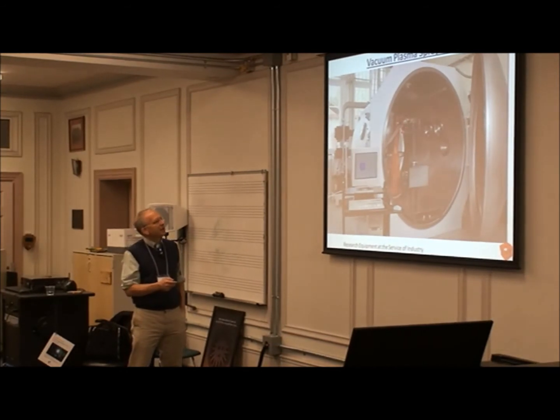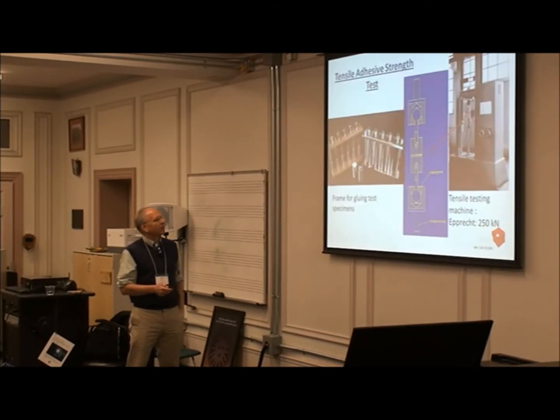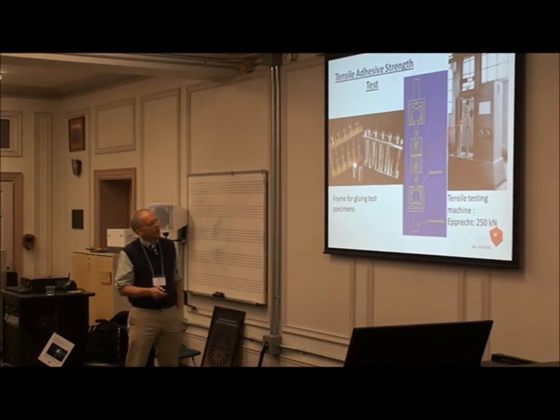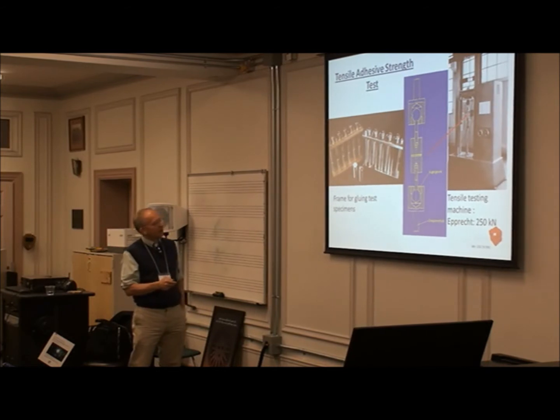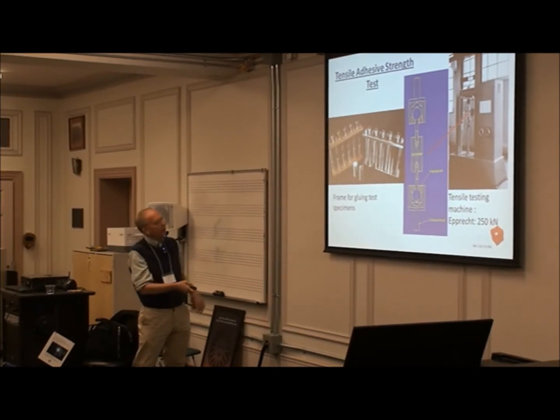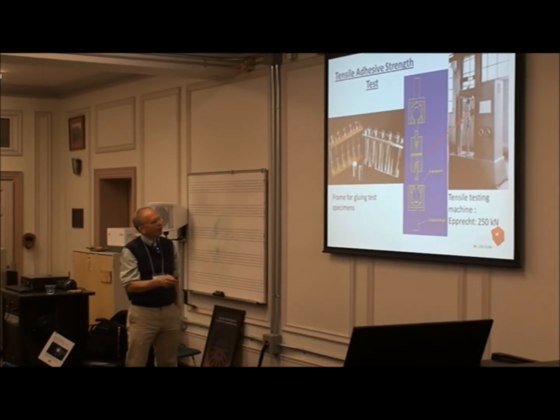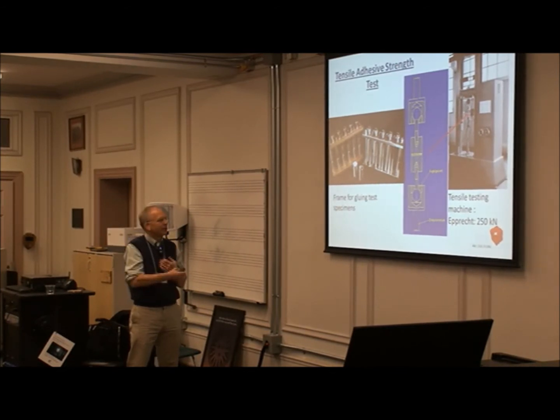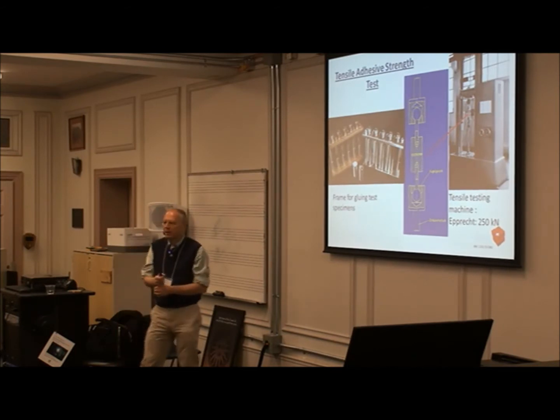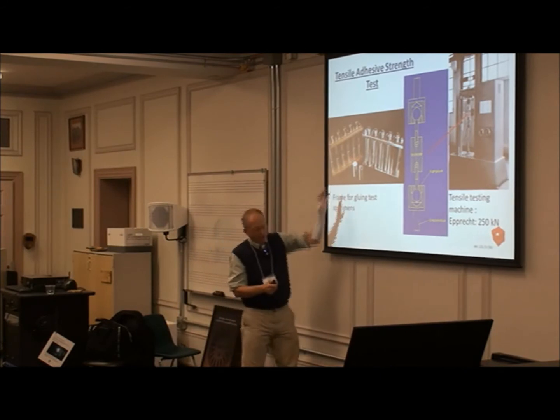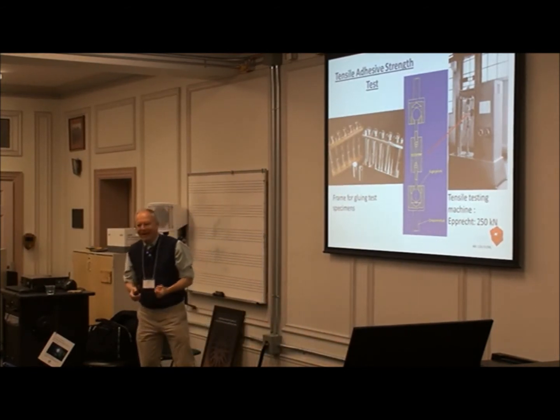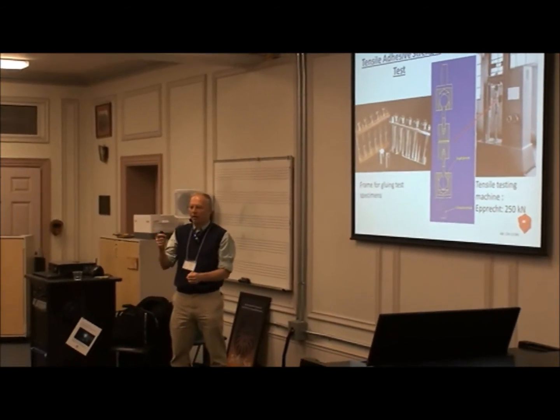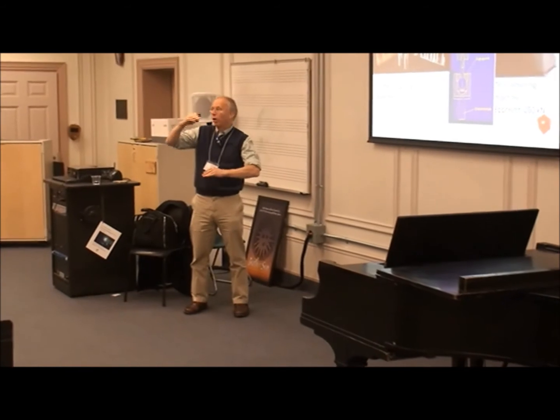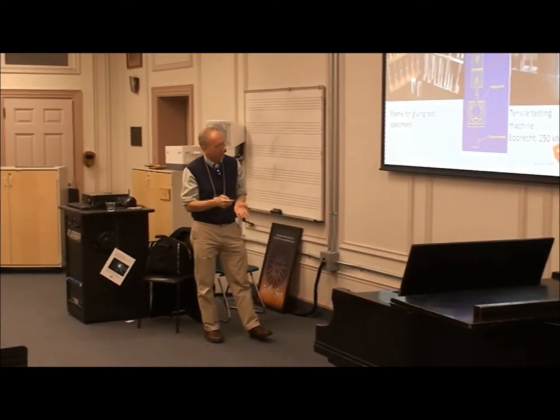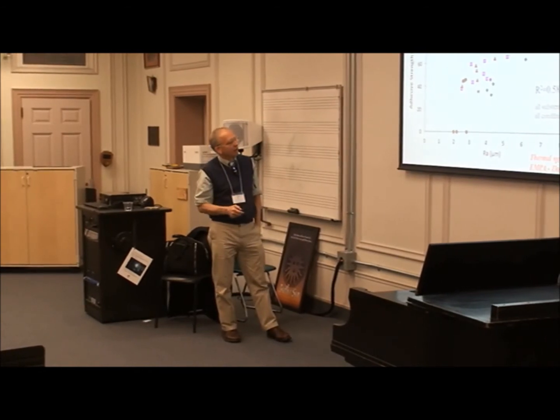So the process, they did vacuum plasma spraying, and this is the facility in Thun where they did that. And then this is their symbol there. So we did these cylinders, then you glue another cylinder to it and you pull it apart in a straight pull with the self-aligning pullers. And so what you have to do is, the glue that you use on this thermal spray coating has got to stick to the other side better than the thermal spray coating sticks to its substrate. And so you have to take a look after you pull it apart to make sure that you had what's called an adhesive failure, so that you actually pulled the coating off rather than a cohesive failure. You might have pulled the coating apart, right? So we only use the adhesive failure ones. And so here's the adhesive strength versus relative area.